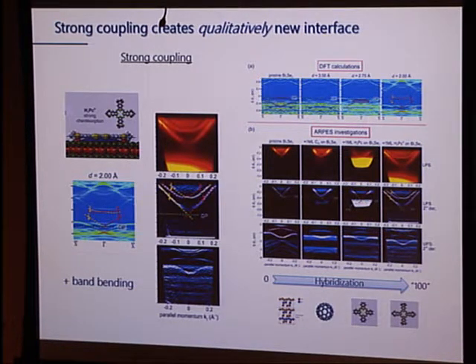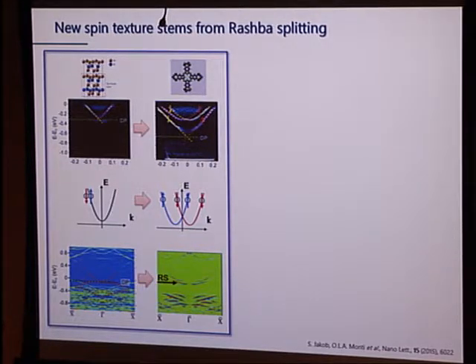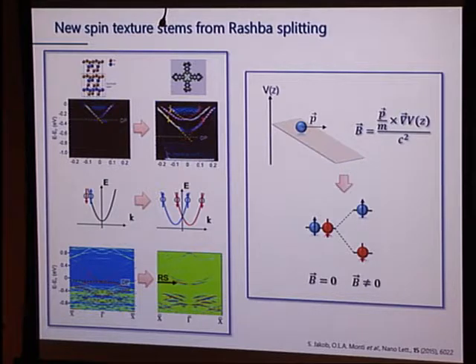So what's going on here? Why do you get Rashba splitting? Well, we see from the calculations that we have strong spin polarization away from all the time reversal symmetric points, so not at gamma, not at X, but away from that, we get strong spin polarization. And this must come about somehow from an electric field. So Rashba splitting just means that you have the creation of a magnetic field by an electron that moves in a potential gradient. That's the usual thing that we would also say for spin-orbit coupling, this means that we must have a potential gradient. The electron movement is, of course, the crystal momentum in the solid. That magnetic field then will split your previously spin-degenerate state into the two spin levels.